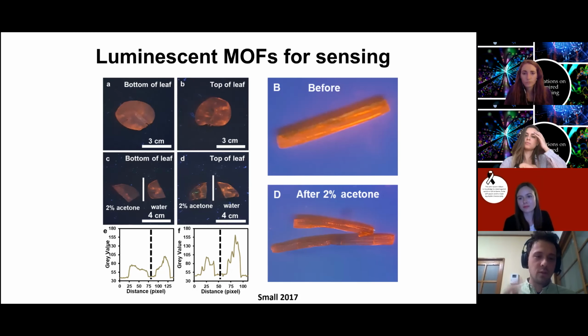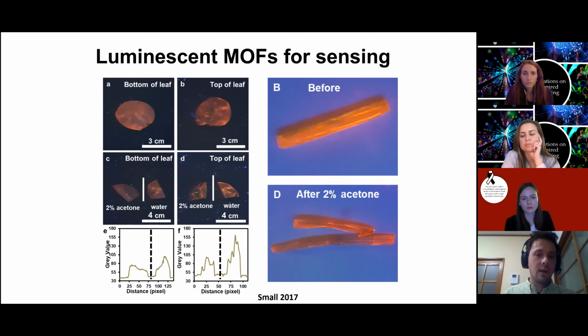But as a proof of principle, in dissecting the leaf, we could see that if we cut the leaf in half and put half in acetone and half not, our fluorescence profile would vary, we get about a 50% drop in the fluorescence upon incubation with acetone. And we could sense down to, I think it was about 0.2% acetone in water using these. Lots of cross-sectioning, lots of UV lights. Cameras don't really capture that well, especially I was often using my smartphone, which, just so you know, will burn out the chip on it, so your selfies will look a lot worse afterwards.